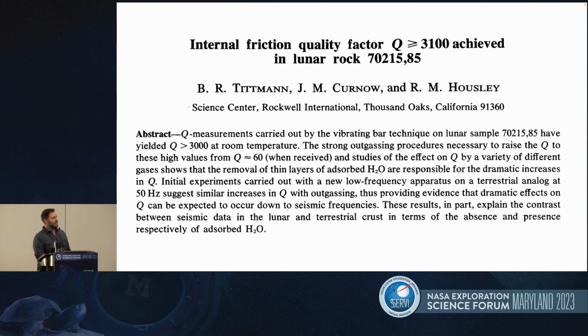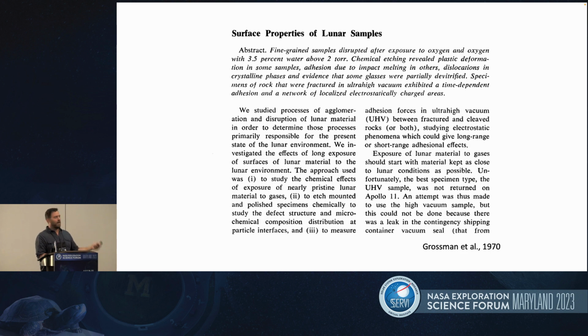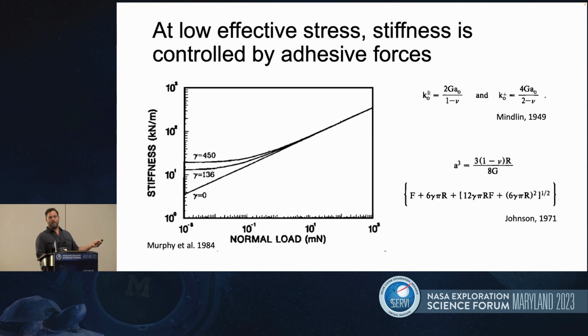So people turned to rock physics, and they did some resonance experiments, and they found that if you bake off your experiments in high vacuum and you remove every single trace of volatiles, then you can recover the sort of high Qs that are observed on the actual moon. And going on to study the effects of small amounts of adsorbed volatiles on the mechanical properties, they found that you also have a change in the adhesion of the particles at very low normal stresses, such as in microgravity or just on the surface of the Earth. In fact, the stiffness, and thus the elastic velocities in materials, are proportional to this adhesion that's fundamentally controlled by the adsorption or the lack of adsorbed materials.